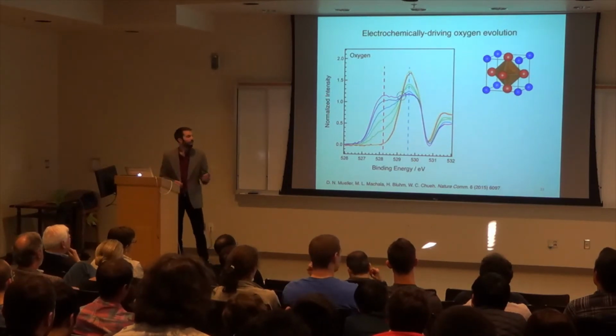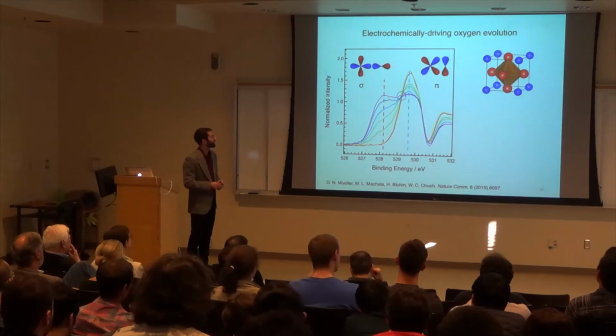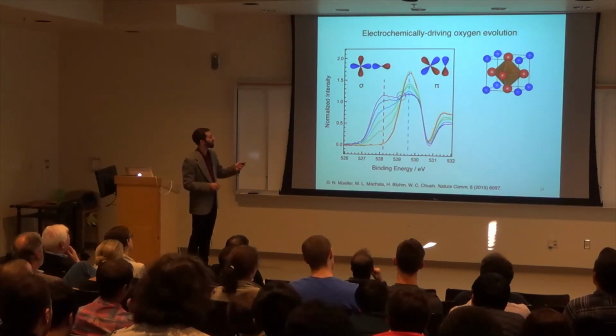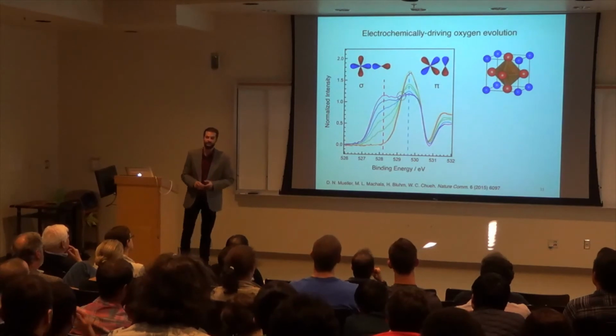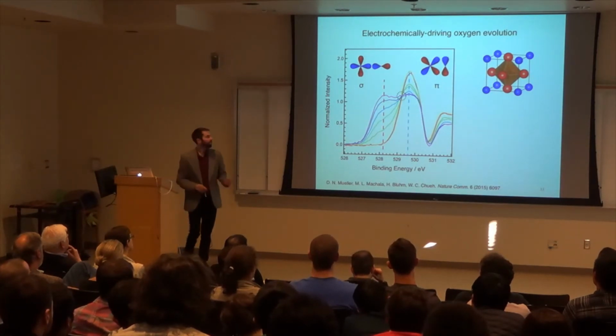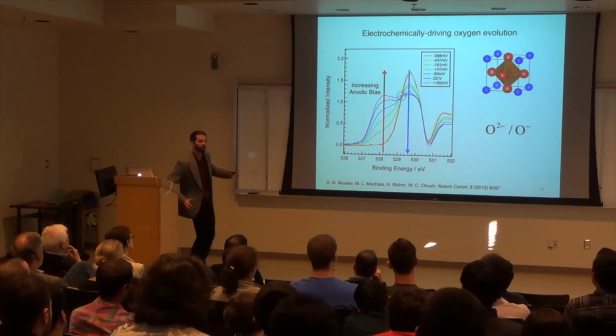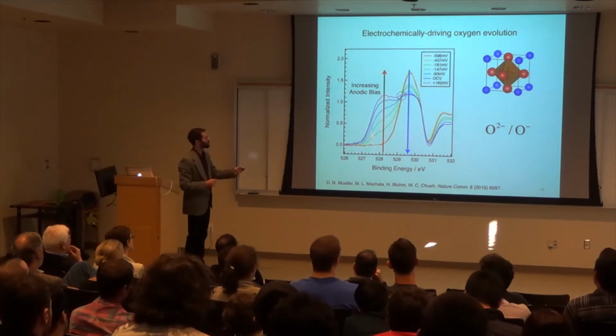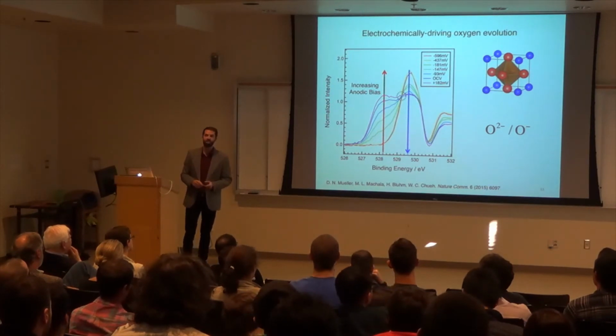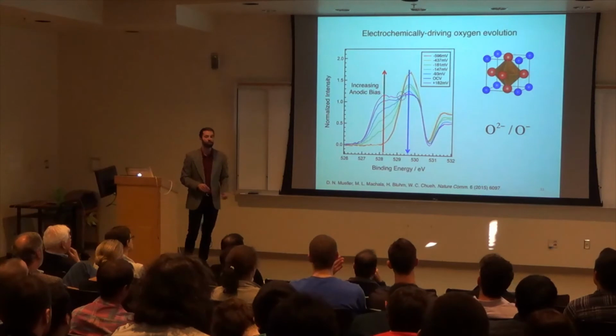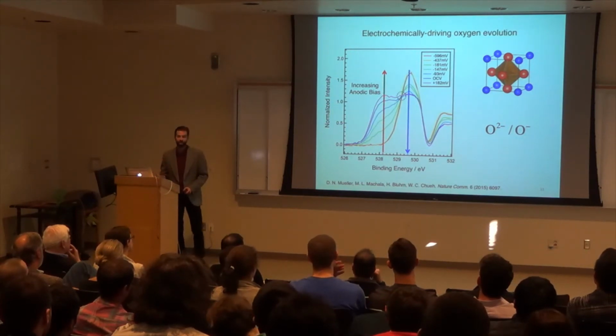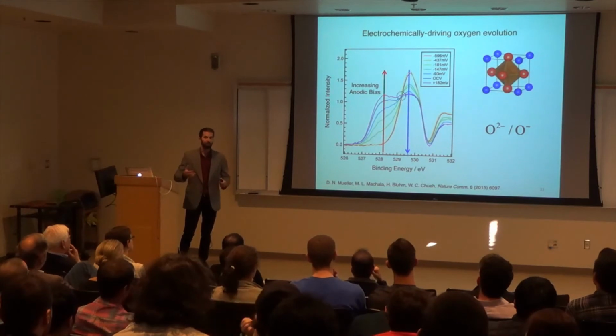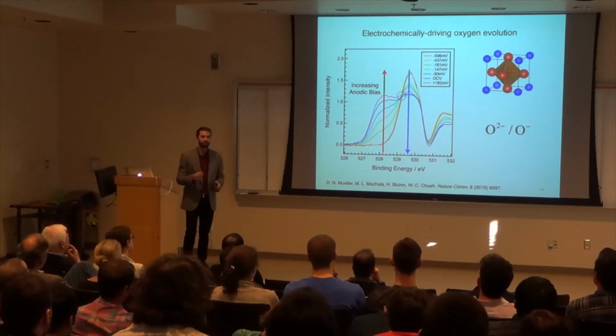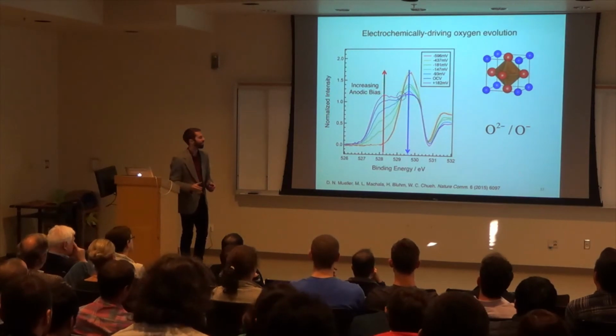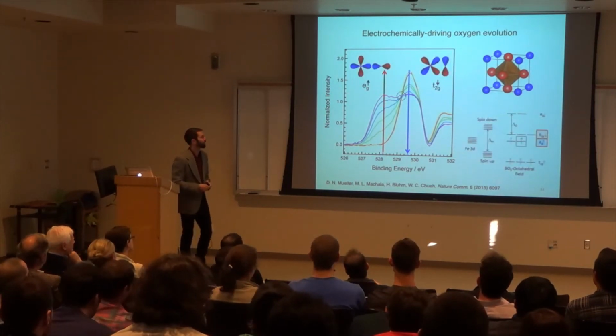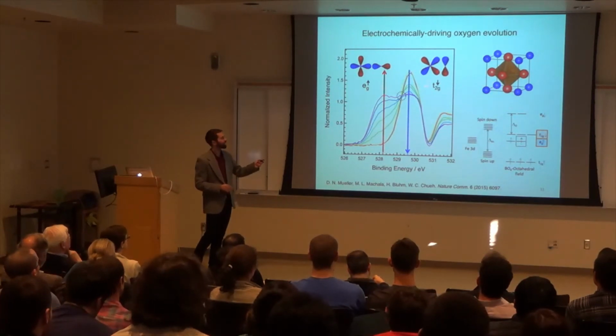Okay? And so when we look closer, we're actually talking about the binding orbitals, the sigma orbital and the pi orbital for the transition metal 3d and the oxygen 2p. So when we apply an increasing anodic bias, trying to drive oxygen out of the material, we actually open up this state. And that signifies that oxygen is changing its oxidation state, meaning we're going more from 2 minus to oxygen minus, showing us that oxygen is primarily the electron transfer species for gaseous oxygen as opposed to the transition metal.